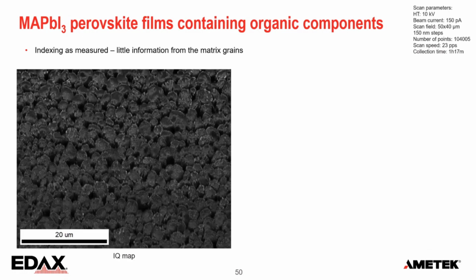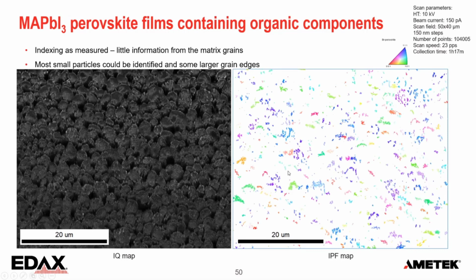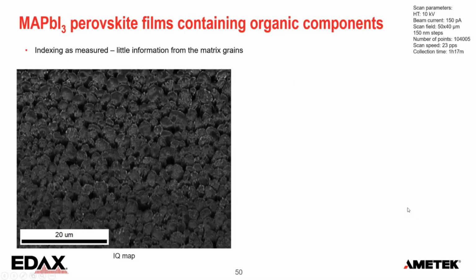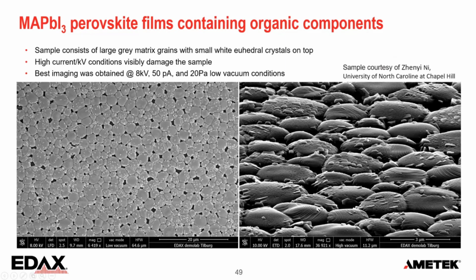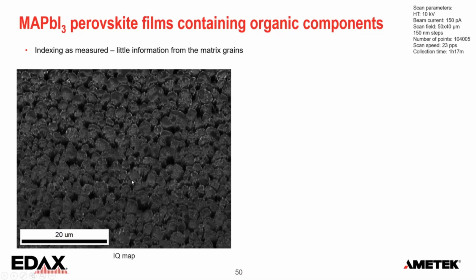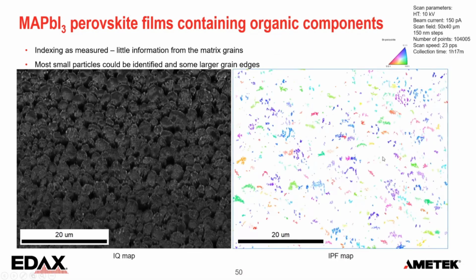And this is what the initial indexing looked like. Again, everything is very dark, meaning very poor patterns, but we can make out those small grains at the top. And that was indexable. Even some of the edges of those larger grains were producing diffraction patterns. Now, if I go back here, you can see that those small grains are not randomly superimposed on the substrate. They appear to be in some kind of epitaxial relationship. So even if you cannot get indexing results from those larger grains, we can actually get information from the little crystal sticking out and infer what is underneath.